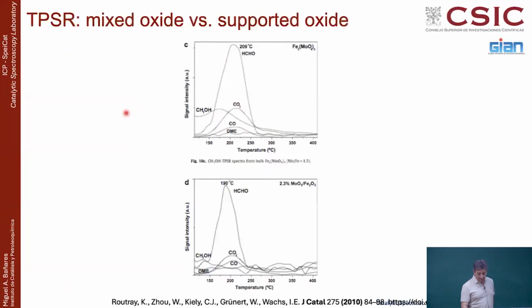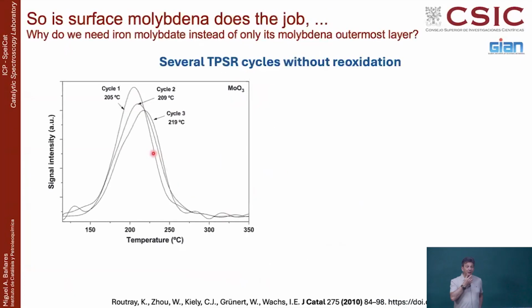Well, here you have even a TPSR profile of methanol on iron molybdate and on molybdenum coating iron. Essentially the same. You even get formaldehyde at lower temperature in the case of molybdenum at the surface of iron than in the case of iron molybdate. So it looks very much alike. Why do I need iron molybdate?